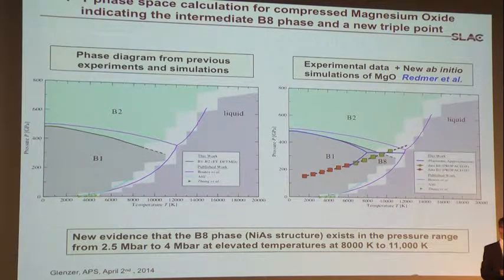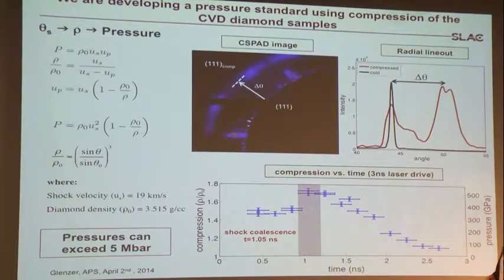And actually, the diffraction data will give us really nice evidence for the new material phases that occur as you shock compress matter to high pressures and high temperatures. So another example is diamond. This is the 111 diffraction peak. You shock compress diamond, and you see how the peak is moving further out, simply because the 2θ gets larger. So now you can do a lineout, and you see how far it's moving.